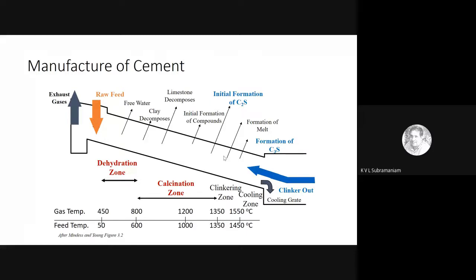Then the limestone decomposes, and I get calcium oxide. And then as the charge starts moving forward, the calcium oxide and the silica start fusing. And basically at around between 1200 and 1350 degrees Celsius, I form the C2S, which is dicalcium silicate. And the tricalcium silicate is formed at a much higher temperature, close to about 1450 degrees Celsius.